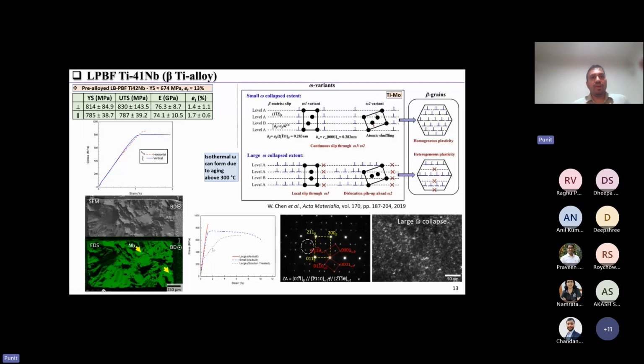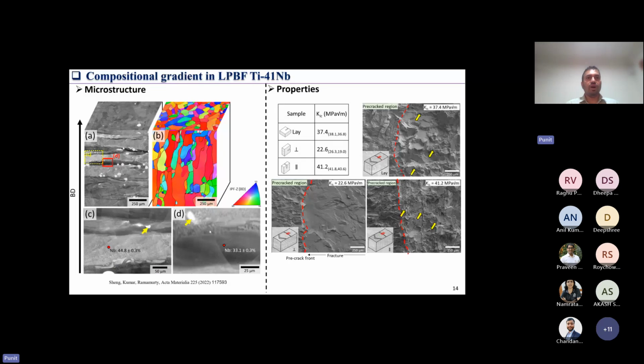So we went ahead and tested these large blocks, and we did some fracture toughness tests to understand the effect of the compositional gradation that we have in our sample. We took these huge blocks and created notches in different directions. These lines here represent the compositional gradation inside the block, and you can see how they are oriented differently with respect to the crack path.